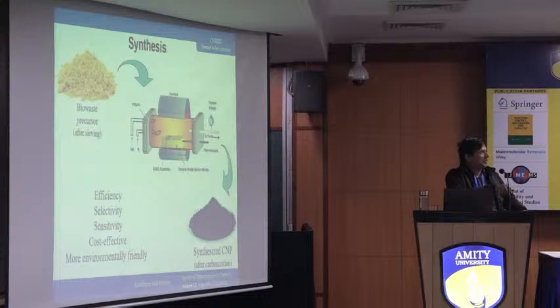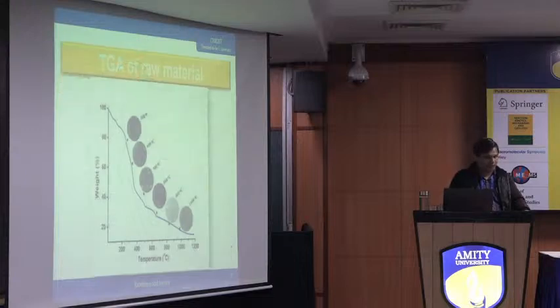Take a bio-waste material, sieve it to certain sizes, and subject it to tube pyrolysis, especially in the tube furnace with inert gases. Here we are using nitrogen. With heating and cooling cycles, with optimization, you will end up with very good carbon nanoparticles. The next question is what temperature you have to synthesize at.